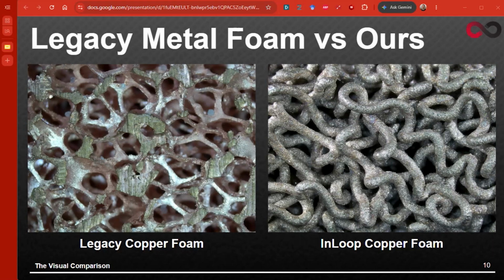Well, if you look at our material, because it is that one continuous thread being bent and entangled over itself, we have a much more organic and curved structure. From the property perspective, this is significant in a few ways. For thermal and electrical conductivity, one thing they really care about is cross-sectional area. So if you look at the legacy copper foams, the actual cross-section between those links is determined based on the random placement of those spheres.